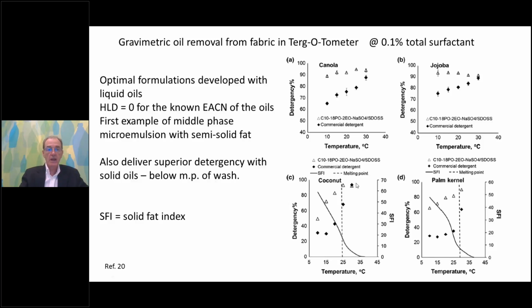They also took the same approach then for semi-solid fats. Coconut oil and palm kernel oil actually have melting points, which we see here by the vertical line, and they again optimized their system for microemulsion formulation of the liquid coconut and palm kernel oil, but then they did detergency at lower and lower temperatures. And we see that the detergency does decrease below the melting point of those two fats, or if you will, as the solid fat index, the solid line, increases, detergency decreases. But the performance of their optimized systems is significantly better than a commercial product, where as soon as you cross the melting point of those semi-solid oils, the detergency drops off significantly. This is a very nice paper I recommend because it's also got a great example of a true middle phase formation from semi-solid fats detailed there.